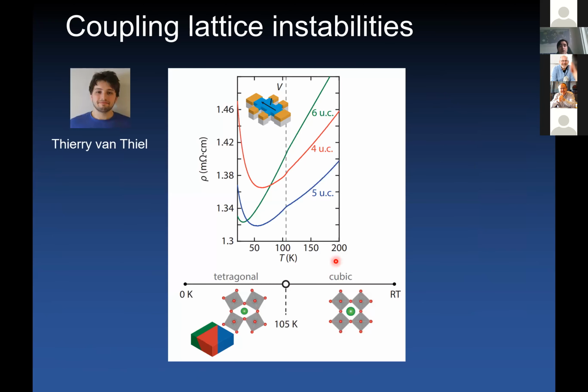Okay, now let's go back to this kink in resistivity that I showed you before. I showed you that in this semi-metallic state, the thin films of iridates on top of strontium titanate display a very anomalous behavior at 105 Kelvin. If you measure 5, 4, and 6 unit cell films, you can always detect a very sharp kink occurring at 105 Kelvin, which corresponds to a transition from a tetragonal to a cubic phase of strontium titanate. So what's going on here?